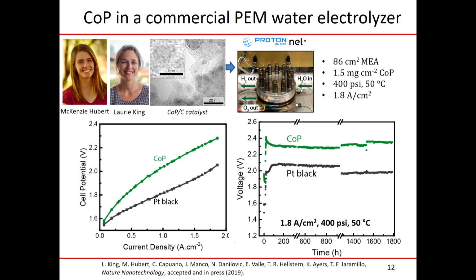They ran this as long as they were willing to, which is about 1,800 hours, and it was stable. And the turnover number here is about 10 to the 5. So it's about 100,000 H2 molecules per cobalt phosphide unit in the system, and there was no sign of degradation at the end. They shut down the experiment because it was the last day of that SBIR. I don't know if it would have lasted another 10 minutes or another 10 years. That remains to be seen. But this is really exciting because this is really the first demonstration of these newer catalyst formulations finding their way and operating well within a true commercial reactor.